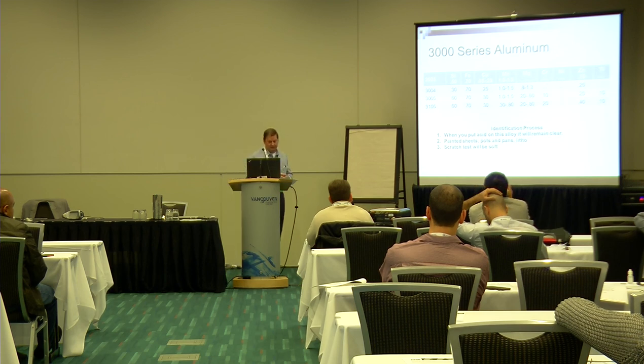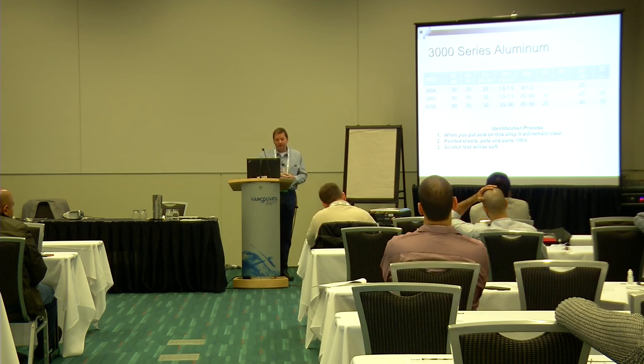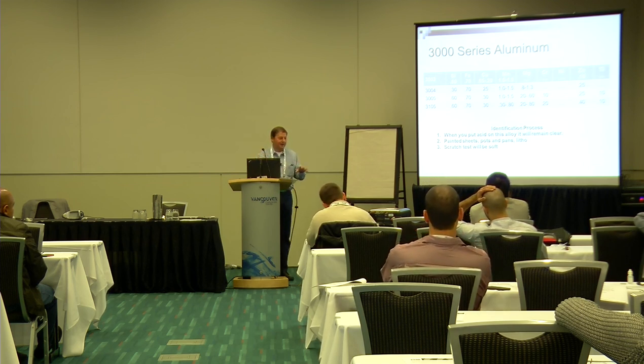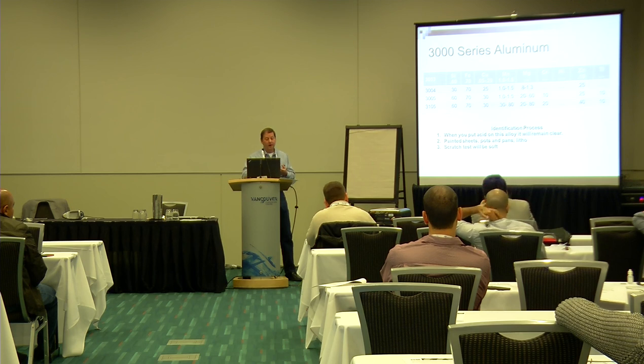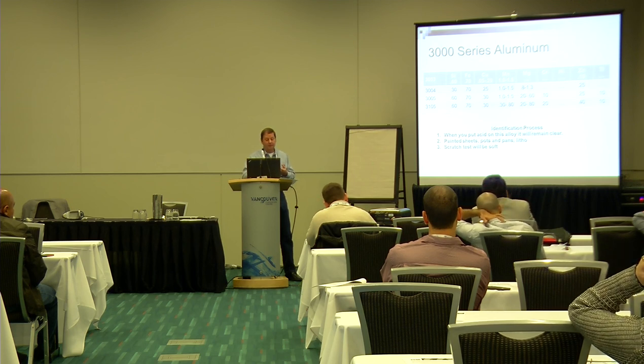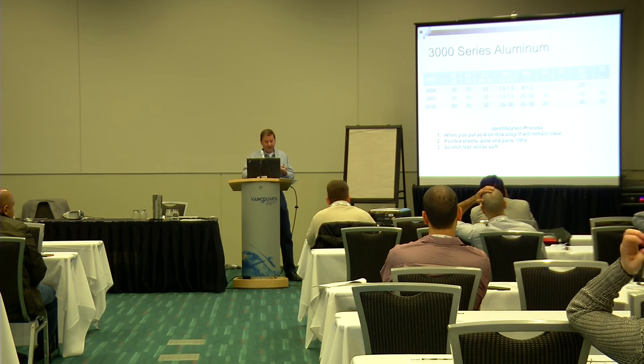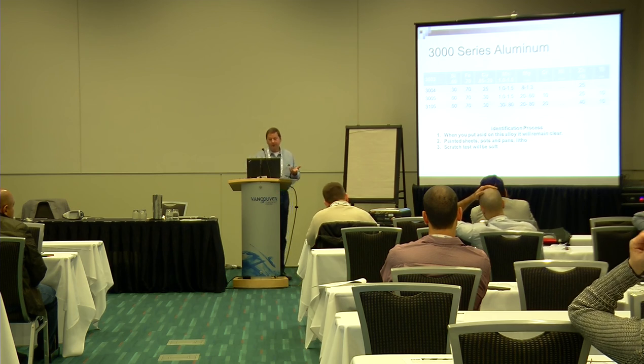3000 series. Now we're looking at the manganese in there. The stuff starts to jump out at you after you look at it for a while. Okay, 3003. What's important about looking at 3003 versus 3004 is if you look at the silicon, you're looking at 0.6 for 3003, 0.3 for 3004. Irons are the same. Coppers are pretty close. Manganese is the same.